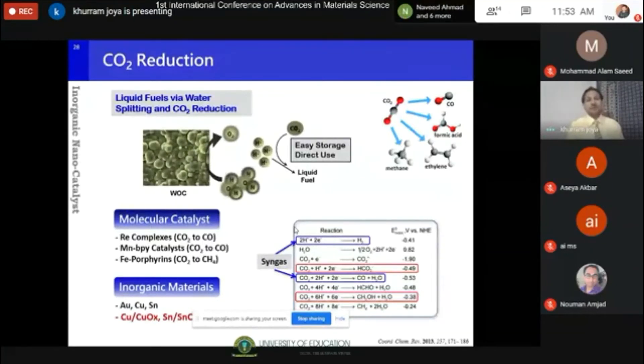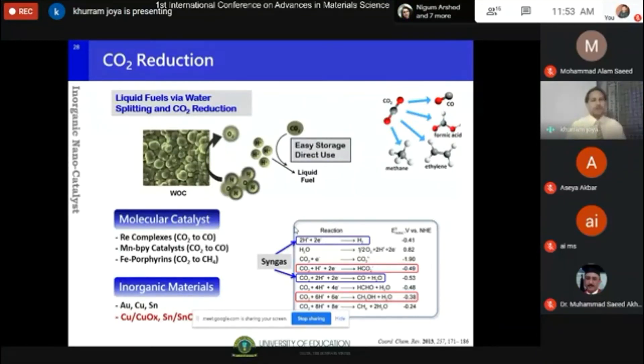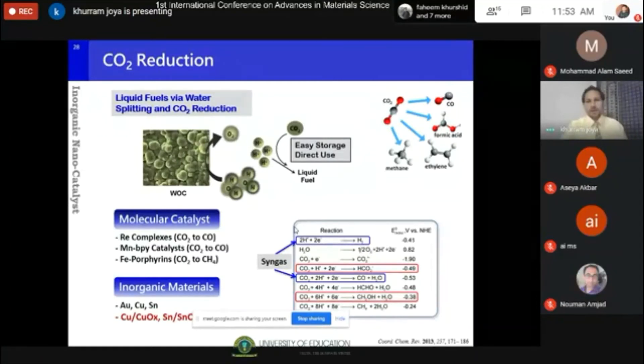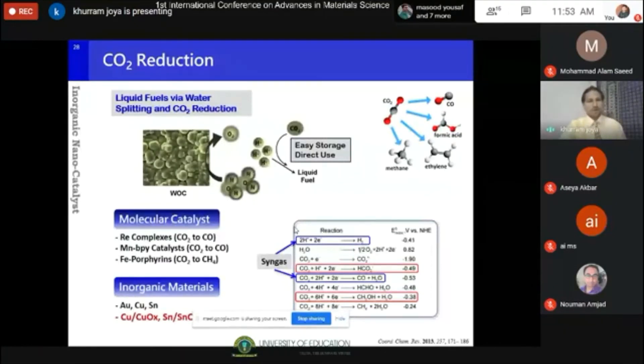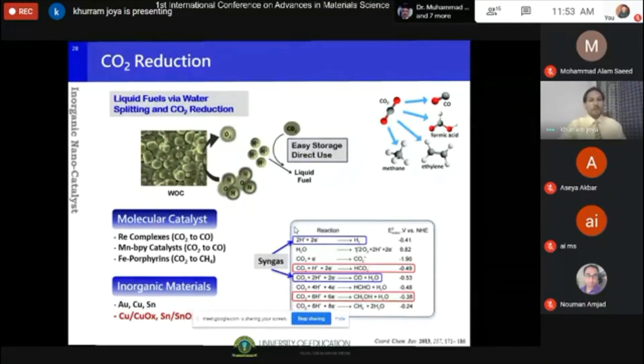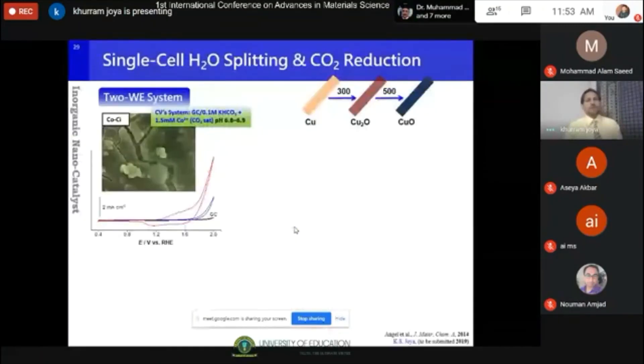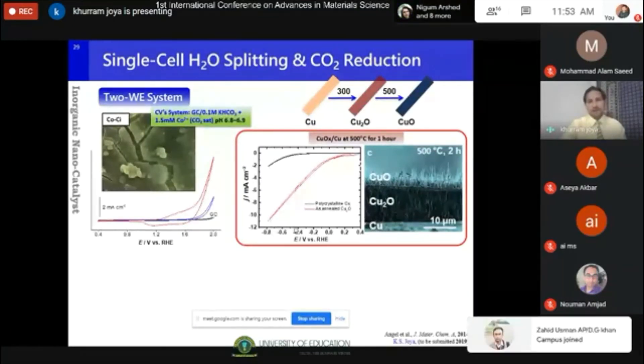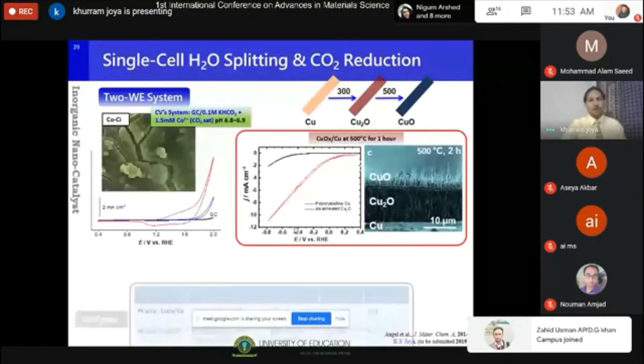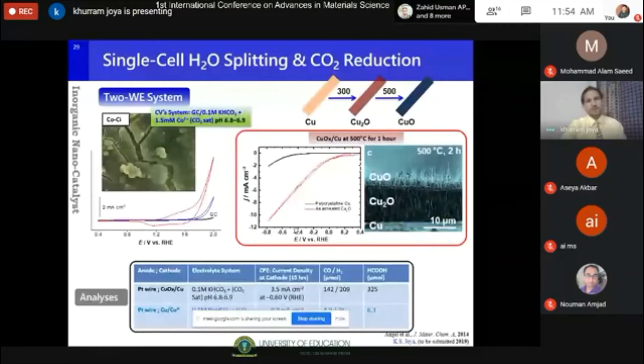CO2 conversion is very challenging research, but it has enormous potential. By tuning the catalyst, electrode potential, and different conditions, you can go towards millions of chemicals starting from CO2 — including fuels, organic chemicals, and polymers. In our work, we developed a cobalt-based water oxidation catalyst that can withstand the CO2 environment, and paired it with a CO2 reduction catalyst — copper oxide-derived copper nanowires — achieving very good conversion efficiency for CO2 to CO and formate.